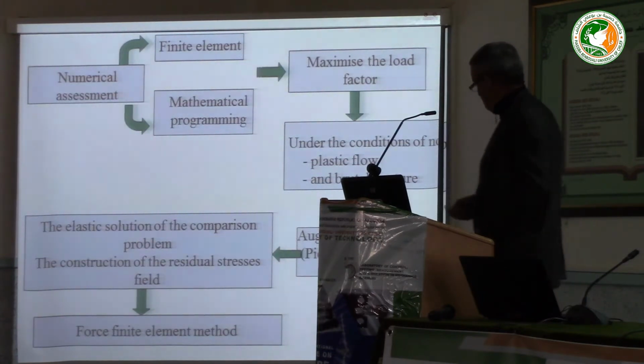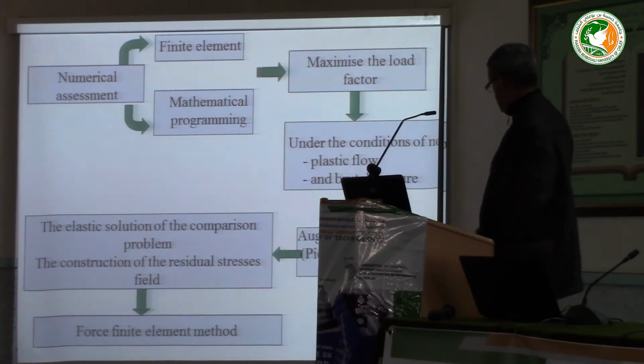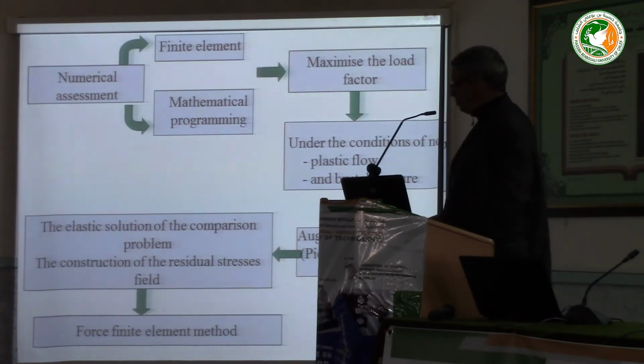So to summarize the problem, we have finite element coupled with mathematical programming to maximize the factor alpha under the condition of no plastic flow and no fracture. We use for the optimization problem the augmented Lagrangian, and we need the elastic solution of the comparison problem and the construction of the residual stress field. In this case, we use the finite element method formulated in force, not in displacement.